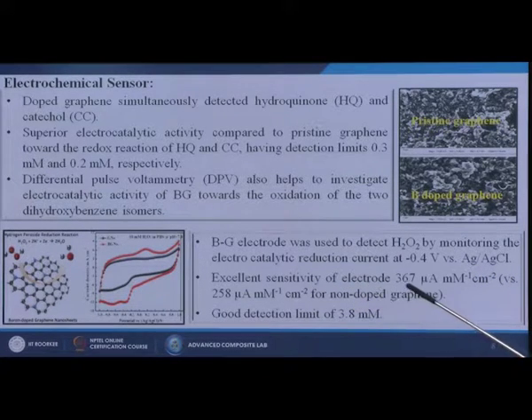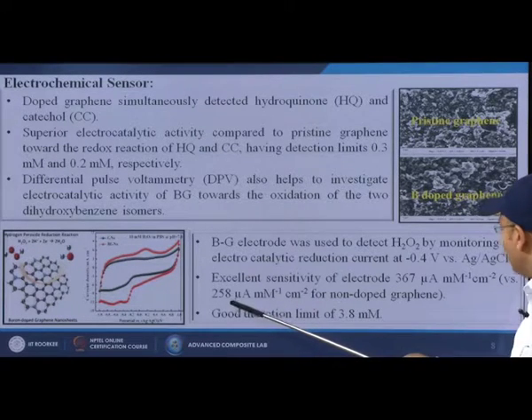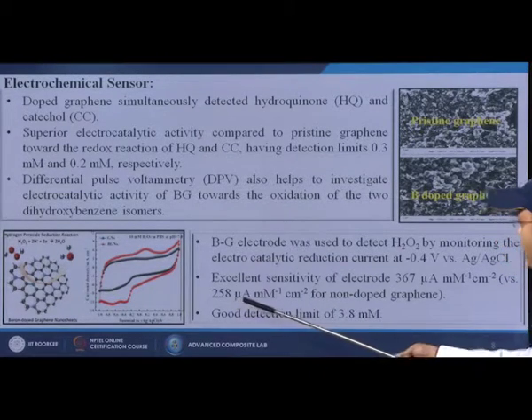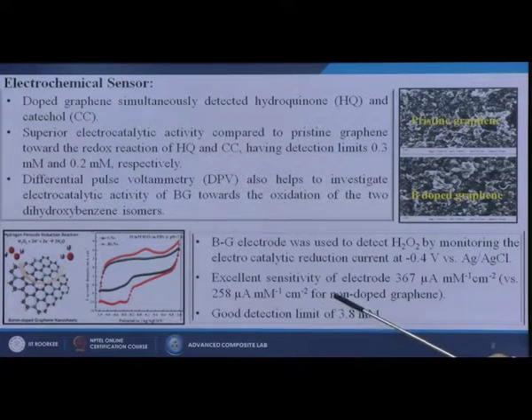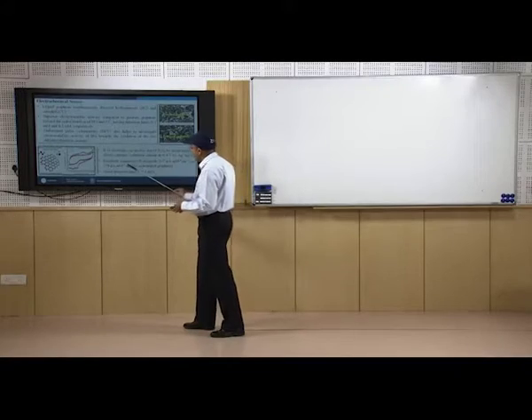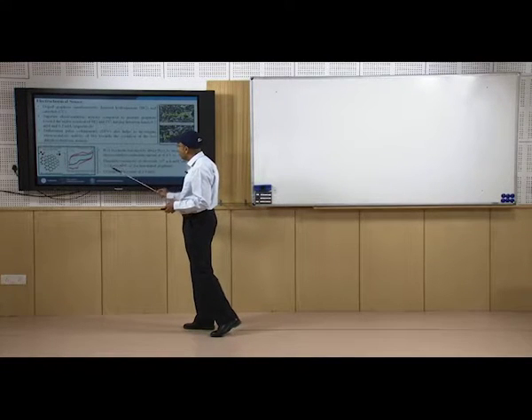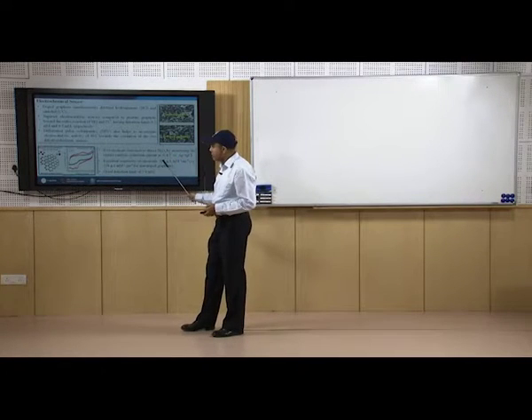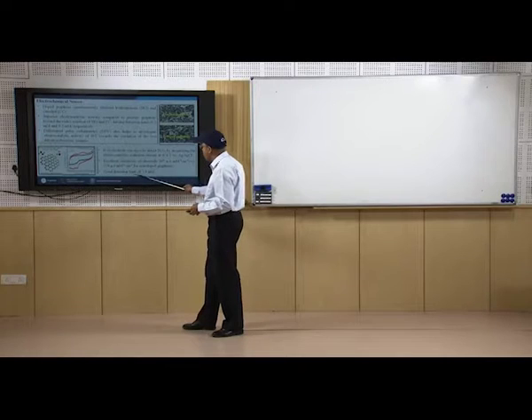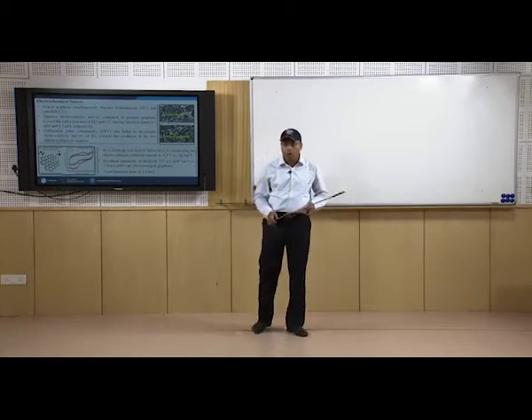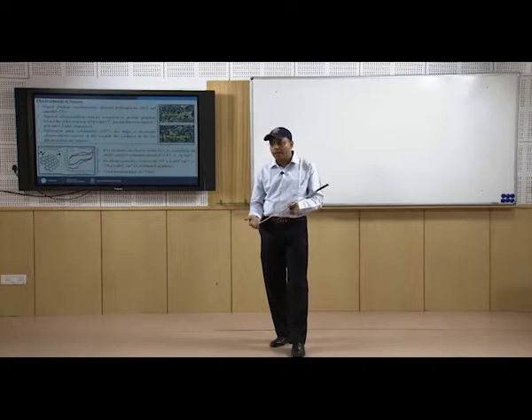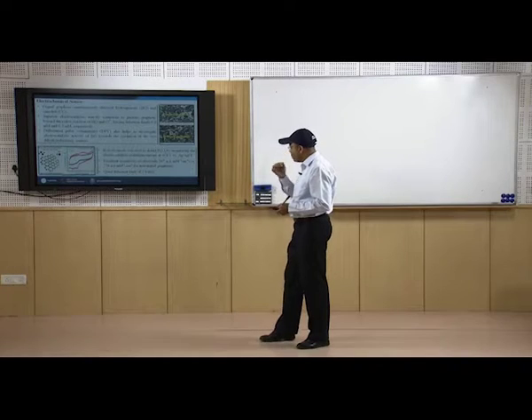Excellent sensitivity of the electrode, 367 microampere per millimole per centimeter square, which is more than the 258 microampere per millimole per centimeter square for non-doped graphene. So, from this case you can see how the sensitivity of the material is increasing from 258 to 367. Not only that, there is a good detection limit of around 3.8 millimole. So, overall the sensing property of the material has changed tremendously by using the boron doped graphene electrode.